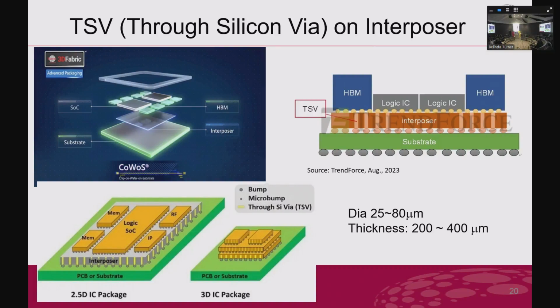And then they use this type of interposer. Currently it is mainly silicon. They form the hole diameter probably around 25 to 80 micron, and the thickness of that interposer is 200 to 400 micrometers. If you see me, we do some practical work in the clean room. The standard silicon wafer we use is 525 micrometers. So basically, it's quite easy to form that structure. We have even made this structure here with our previous process.